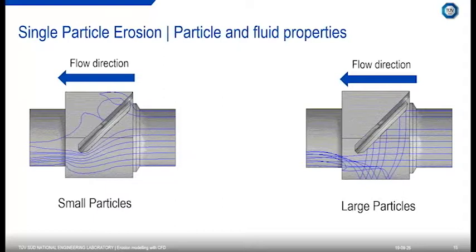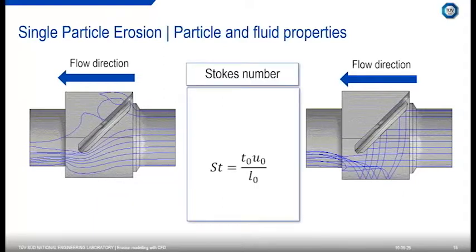size. So on the left-hand side we have smaller particles, and they have lower inertia, so they will follow the flow, whilst the larger particles detach from the flow, they have higher inertia, and they impact the wall. And the particle size distribution that we're talking about can vary widely from flour to millimetres, for example, in oil and gas applications. So a helpful way to characterise this is through the use of the non-dimensional Stokes number, and this characterises the behaviour of the particle suspended in a fluid flow, and it's useful in helping understand the situation where our particles will impact the wall.